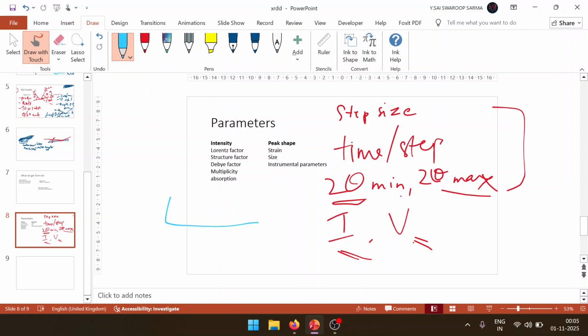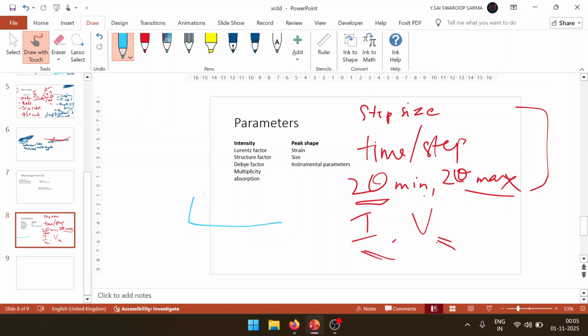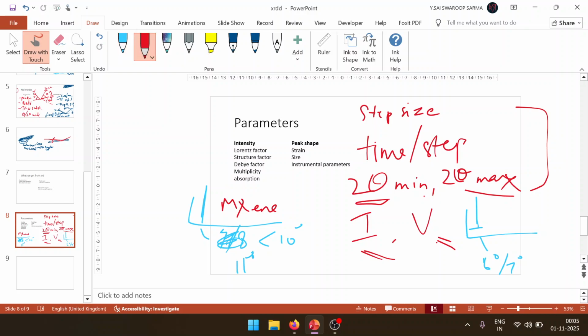I'll tell you an example. Let's say you want to do an XRD of a MXene material. Your first peak occurs around 7 or 8 degrees, if I remember correctly; it's less than 10 degrees, between 5 and 10. Similarly, if you take a MOF material, the first peak comes around 6 or 7 degrees. Actually I think that was not 7, it was 11 degrees. I don't remember very correctly, I did it many years ago, but still it is less than 10 to 15 degrees. So in MOFs this is the case.